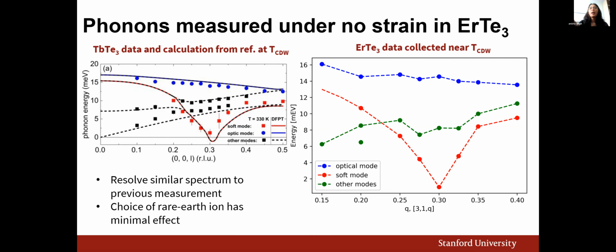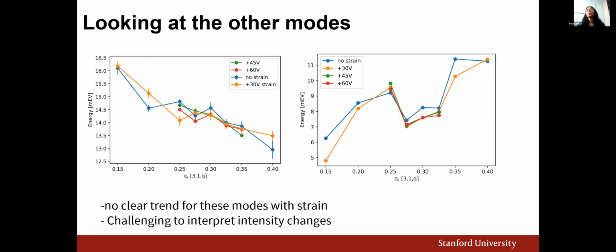Okay, so once we've established that we're looking at the right thing, we want to start applying some strain now and see how things change. So I'll start off with the less interesting bits, which are these higher order modes. And we see that in general, these modes are not really evolving in any kind of systematic way as we apply strain. So on this slide, I'm still plotting things in terms of the absolute voltages that we apply to the piezoelectric stack. Here, positive voltages correspond to positive strains, so tensile strains. But we can also observe how the lattice is responding through the application of these voltages and then convert these into real strain values. So the rest of the data will be plotted in terms of those real strain values.